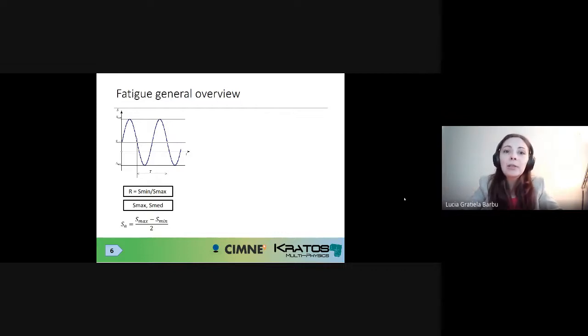Okay, so we have a cyclic stress state at each integration point, and based on this stress state we can compute a reversion factor. Stress ratio, it's called, this R factor, which is the ratio between the minimum level of stress recorded at that integration point and the maximum level of stress recorded at the same integration point. So throughout our geometry, all of the integration points inside all of the finite elements have their own specific stress ratio, okay? Of course, we can compute what is the maximum level of stress inside the whole geometry, what is the maximum stress ratio inside our geometry, etc. But just to explain, what is this stress ratio?